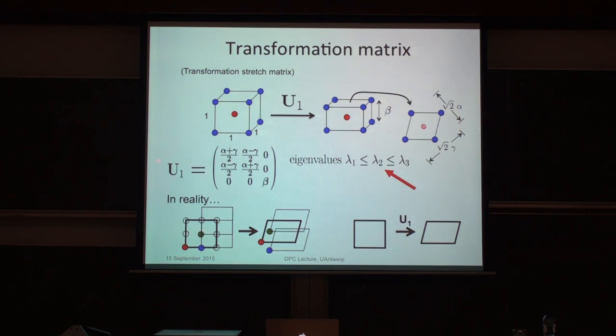So there might be a large number of Bravais lattices, simple lattices determined by three linearly independent vectors. And during one of these phase transformations, each one of those undergoes exactly the same linear transformation. If that didn't happen, you would destroy periodicity. But the different lattices can displace relative to each other. That's called shuffling. And so that's the typical picture of a phase transformation in a complex lattice. And in that case, we identify this transformation stretch matrix with the linear transformation of any one of those lattices.